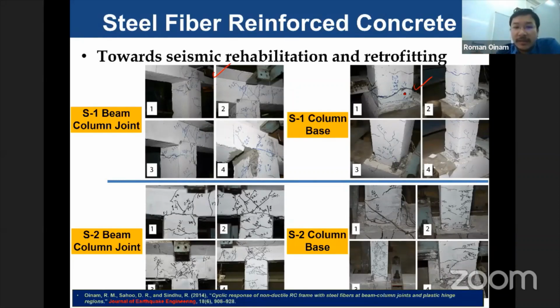If you look here in the steel fiber, there will be lots of micro cracks, but the major crack does not exist. But in the case of the plain concrete, micro cracks are very few, but major shear cracks have developed. So this is more dangerous than the micro cracks. Sometimes we prefer lots of micro cracks because they distribute the stress. But when there is a major crack, the whole damage is concentrated at one point, and the chance of collapse or fracture is quite high. So this is the advantage of our steel fiber we can observe here. It distributes the stress uniformly.